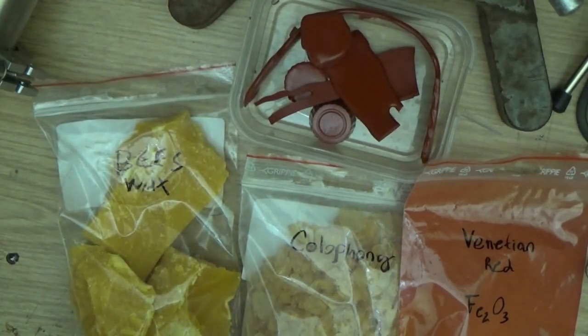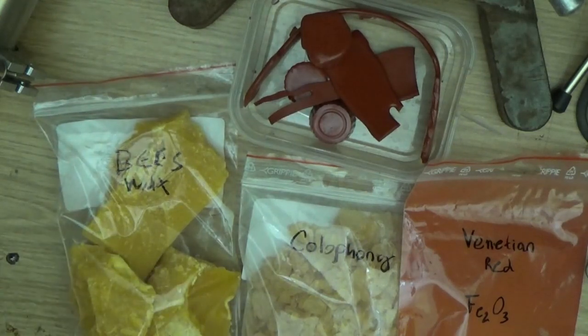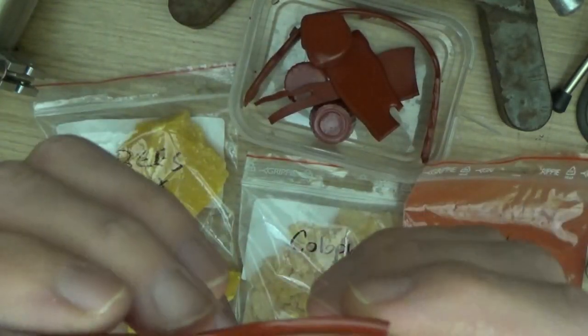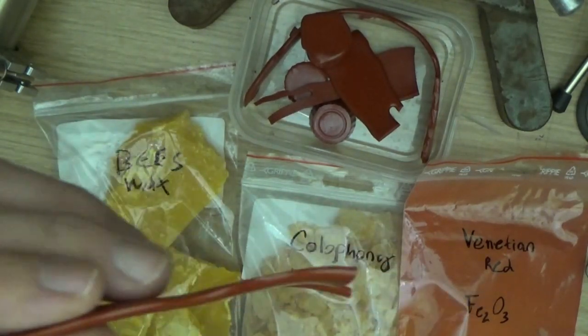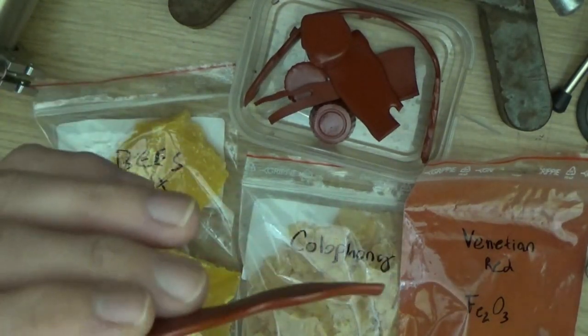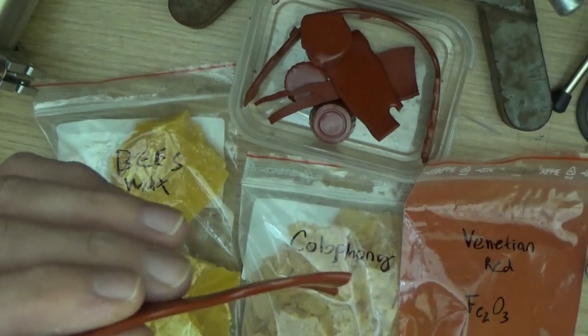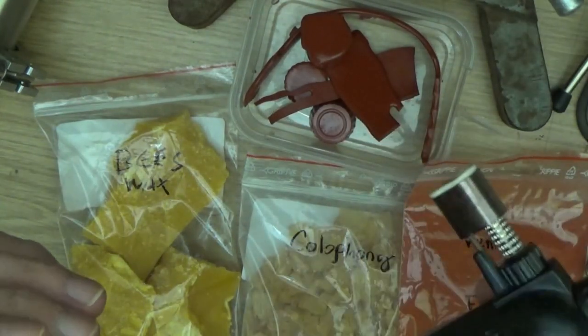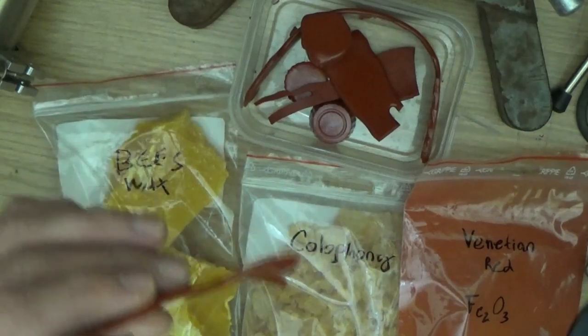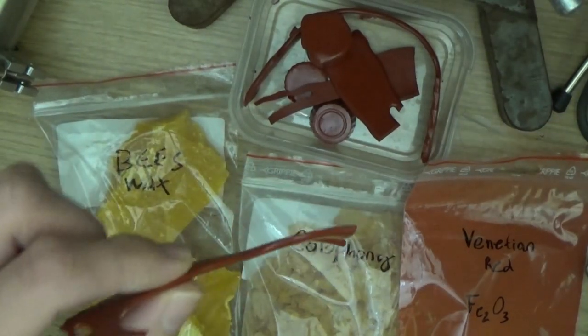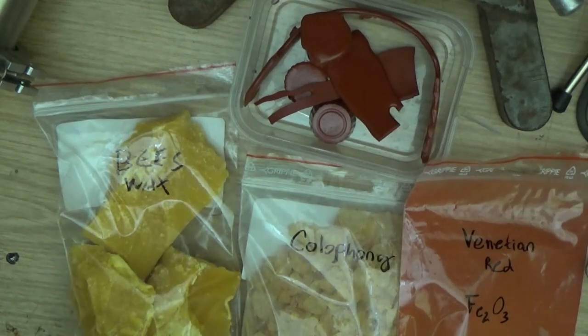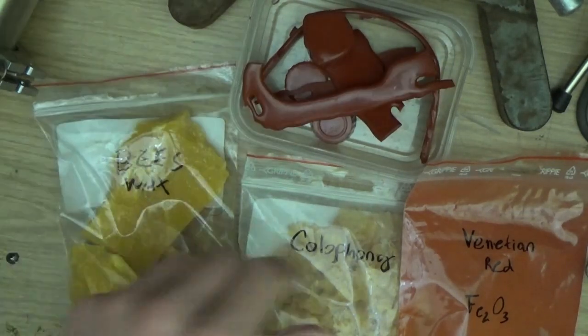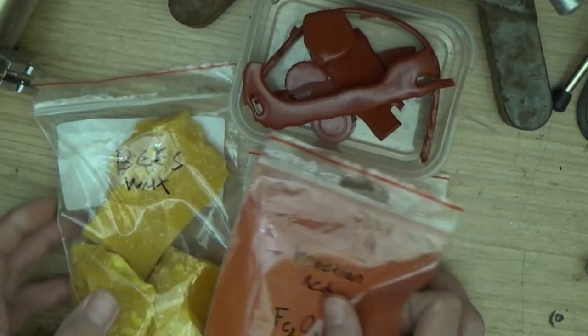I like this solder thing, so I've made these thin slivers just by pouring it out on some baking paper. And my hope is that I can just, no, not my hope, I've done this. You can heat the part with a little torch, just a small crème brûlée torch. And then you apply the wax to the hot surface, you just draw whatever shape you want. And then you do that on both your halves, and then you just heat them again and press them together.